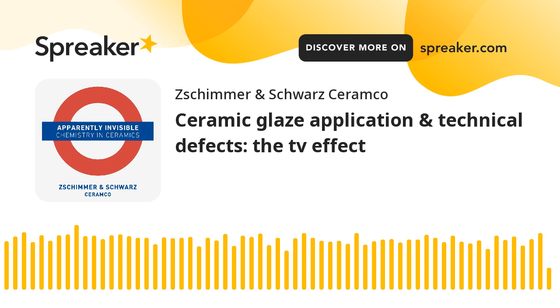and the decrease of the surface tension makes the water move freely between the suspended particles. And the deagglomeration, together with the decrease of the surface tension, leads to a perfect leveling action that prevents the formation of the cathode-ray tube effect on the edges of the tile.